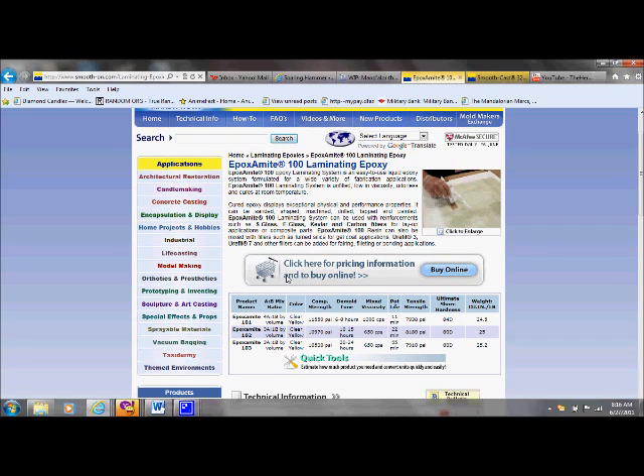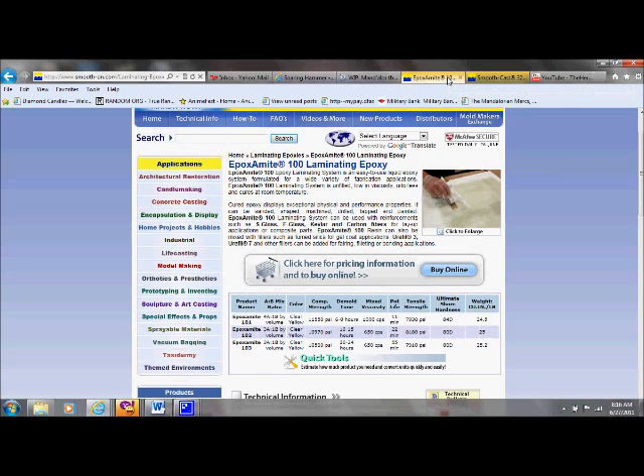The Epoxamite has a tensile strength of 7,930 psi, which is tensile strength per square inch. Now, if you go over to Smooth Cast 321, this only has 3,100 psi. So it's 3,100 tensile strength per square inch. So it is more than doubled. The tensile strength itself is more than doubled with the Epoxamite, which makes it stronger, which means the pull ratio is a lot stronger for the Epoxamite 101. The compression strength is 11,550 psi, whereas your Smooth Cast 321 is only 4,500.